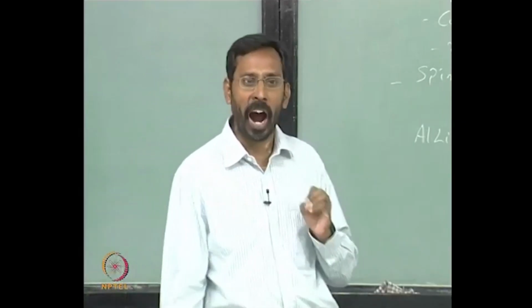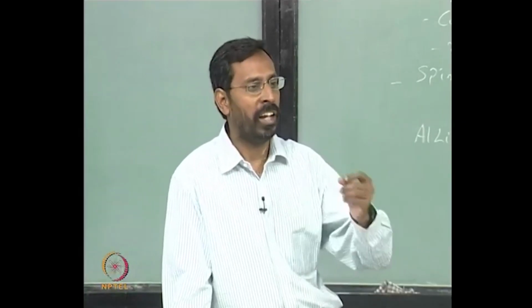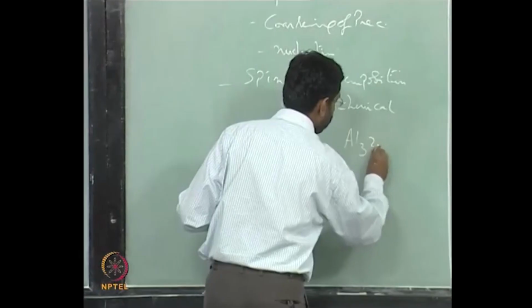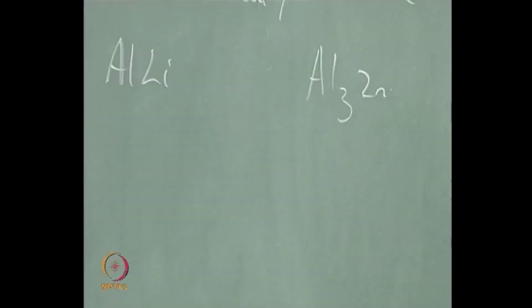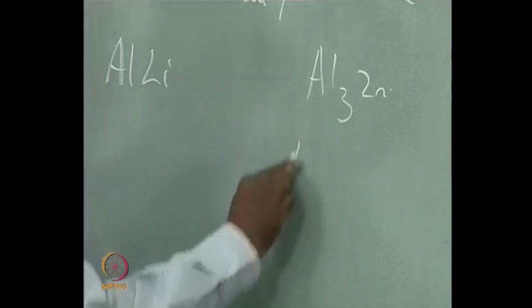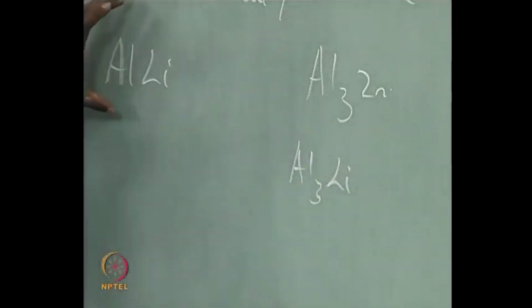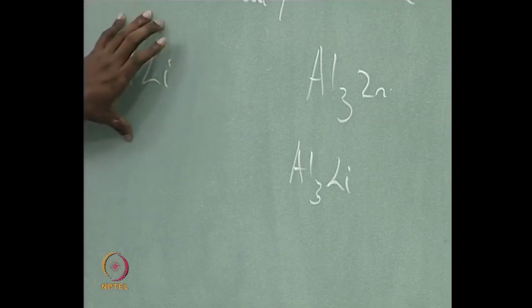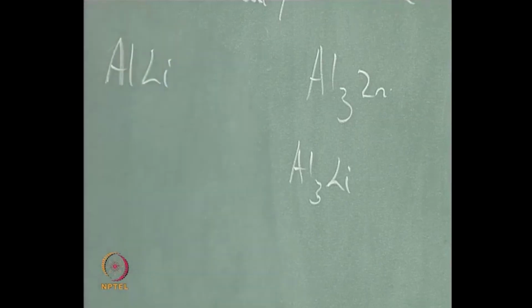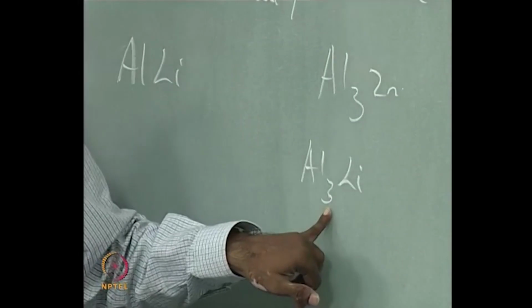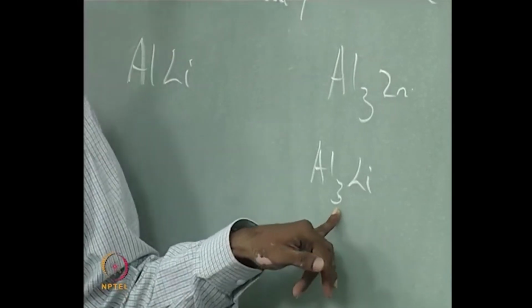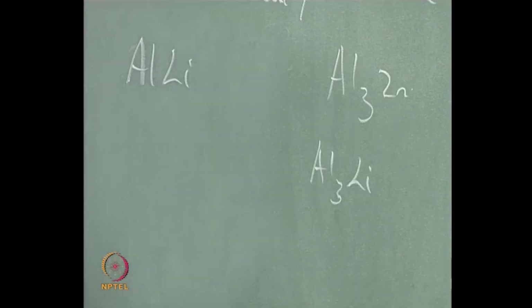So what they have done is they have added certain heterogeneous nucleating sites. For example, Al3Zr is used as a nucleating site for the Al3Li. Incidentally, when I started, I said that in the aluminum lithium phase diagram AlLi is the stable phase, but this is not the one that you get when you do age hardening of aluminum lithium alloys. What you get is this phase Al3Li, exactly for the same reason why you get GP zones in aluminum copper alloys. Al3Li is exactly similar to Ni3Al. It is what we call the L12 structure.